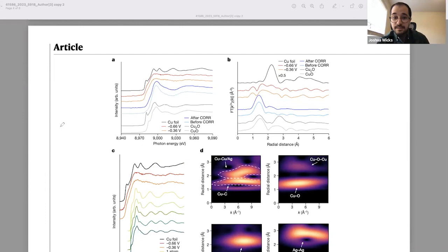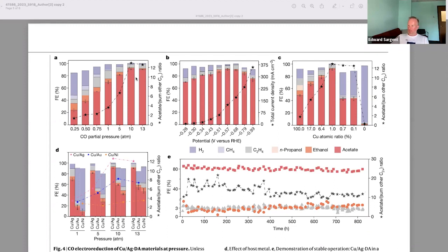Yeah. So Jun Li was our XAS lead in this project. Several other co-authors on the paper assisted him in experiments at several different synchrotron facilities around the world. And so in these experiments, we took our catalyst material, inserted it into an operando XAS cell, where we can probe the local atomic structure of our catalyst material before reaction, after reaction, and during reaction. And so in these figures here, we show a variety of different comparisons, both while under an applied voltage.